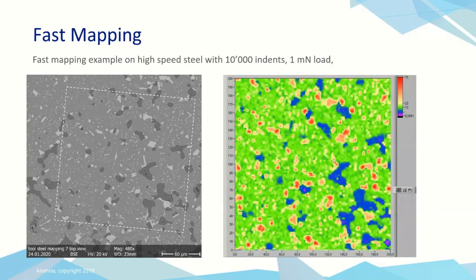So if we look at that surface, here's the hardness map. So every pixel of this image is 1 nanoindentation. And so you can see the soft manganese sulfide grains in blue. That's the lower end of the hardness scale. The very hard carbides are in red, high at the top of the scale here. And green is sort of intermediate. This is the ferrite matrix around. So this allows us to map those mechanical properties with a very high degree of precision.